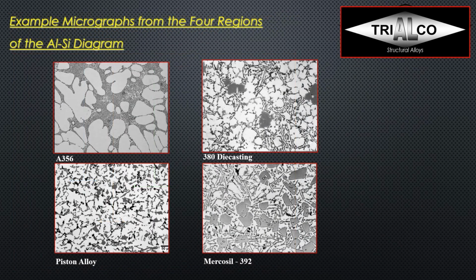We see here a few example micrographs from the four regions of the aluminum silicon diagram. On the left top, we see the A356 alloy. The light gray areas, those are actually the alpha aluminum. So this is pure aluminum that solidified first. You remember when we're falling below this curve, liquid, and then we have the alpha phase solidifying, and in this case it would be aluminum first.